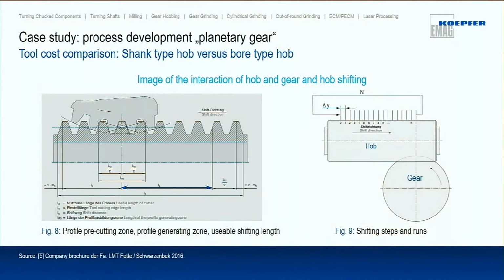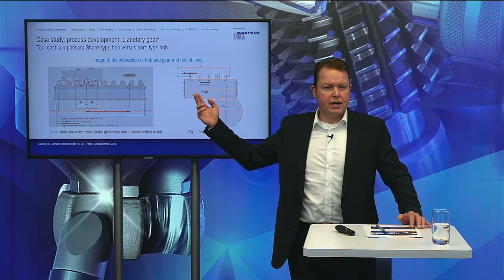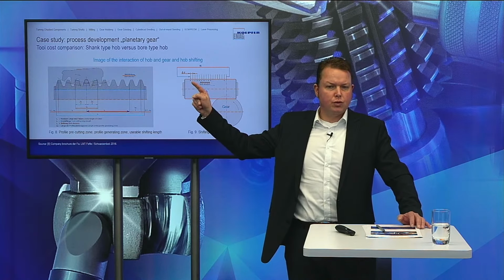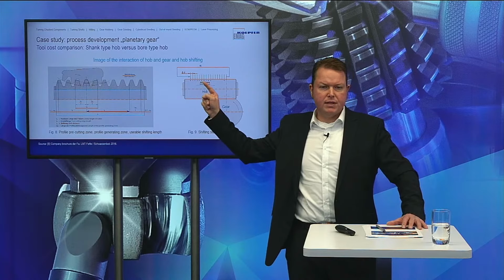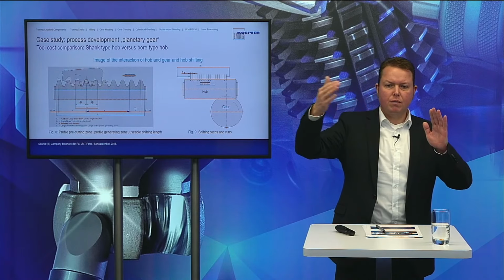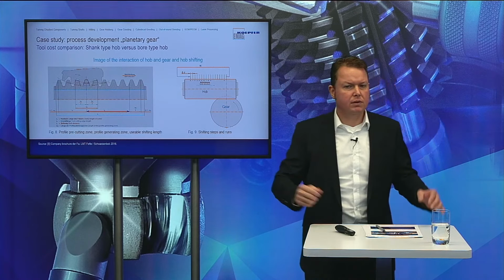And we are going to shift this hob. That means in the picture on the right side, you can see this. We have an initial position 0. We cut a workpiece on this shifting position. Afterwards, we make a certain shifting step, delta y, to the next shifting position. There we cut the next piece, etc., ongoing this way until the whole hob has been shifted through. And then we may start from the beginning again. And this shows now what I mentioned earlier. In case of dry hobbing, we would tend to select a relatively huge shifting step in order to make sure we have uniform introduction of heat into this tool.